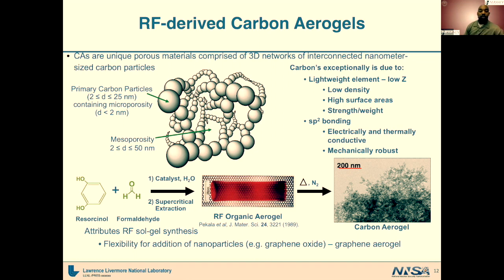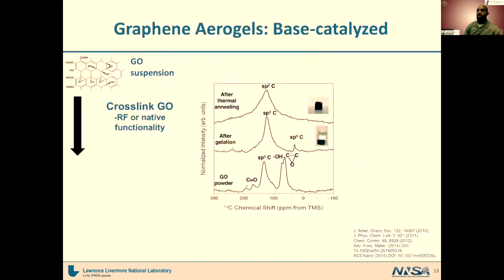One of the reasons we really like this particular method for making carbon aerogels is that it gives you a lot of flexibility. You have flexibility in the synthesis to tune the final morphology: things like the pore size, the surface area, the particle size, the density. But you can also incorporate different sorts of nanoparticles, for example graphene oxide, to end up with a graphene aerogel, which has a very different morphology and different properties from the carbon aerogel I'm showing here. So when working with the graphene aerogel, we tend to start with a graphene oxide suspension, so GO.